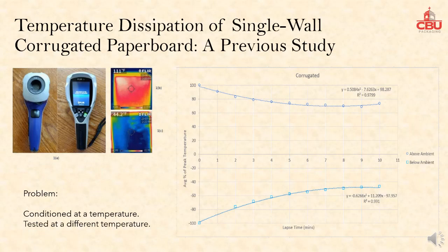In a recent study on temperature dissipation of single-wall corrugated paperboard, the temperature dissipated very quickly from the moment the paperboard was removed from an environmental chamber. This creates a problem. The test sample is conditioned at a certain temperature. However, it is tested at a different temperature. In this recent study, temperature was measured using an infrared camera.